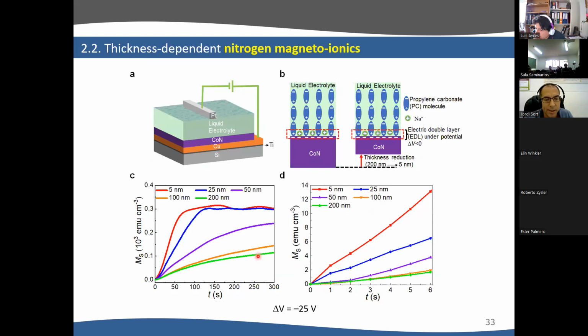So what we did is to reduce the thickness of the cobalt nitride layer. And you can see here that when you reduce the thickness of the layer from 200 nanometers to 5, especially if you zoom in at the beginning, for 5 nanometers, already in 1 second, we generate magnetization. So we can induce this off-on transition and reduce the time from 25 minutes to less than 1 second just by decreasing the thickness of the layer.